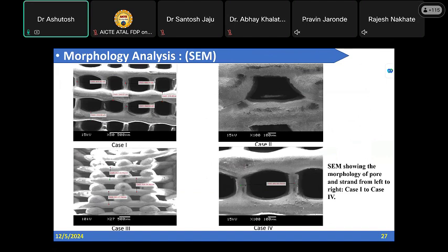These are the morphological SEM images of the 3D printed scaffold which I printed by using the bioplotter. You will find it does not consist of only macro pores. This is basically a macro pore, but it also consists of micro pores. In any kind of scaffold printing, we require micro pores and macro pores, because the micro pores are responsible for the adherence of the cell line, while the macro pores are responsible for the migration of the cells and transport of the required carbohydrates and other things required for angiogenesis. So both macro and micro porosity are required in the case of a scaffold.